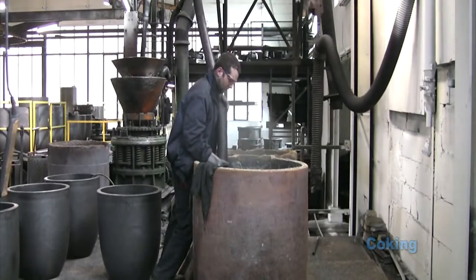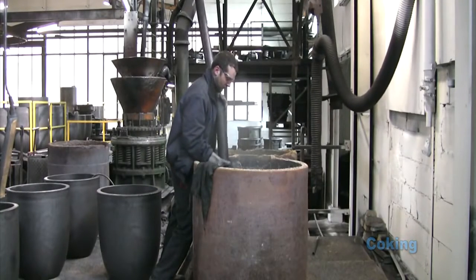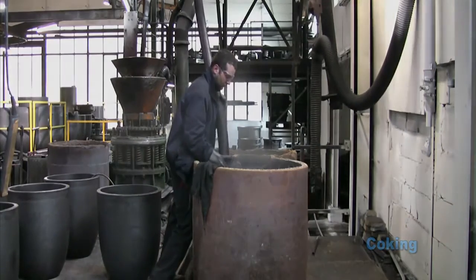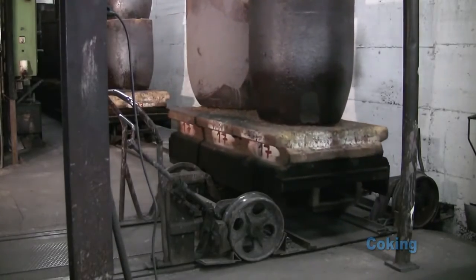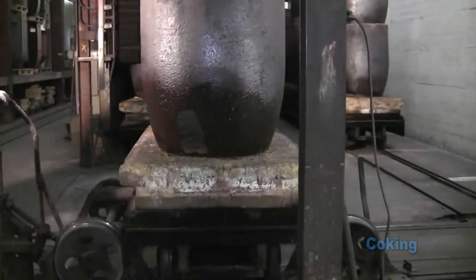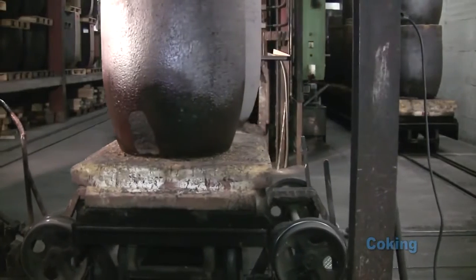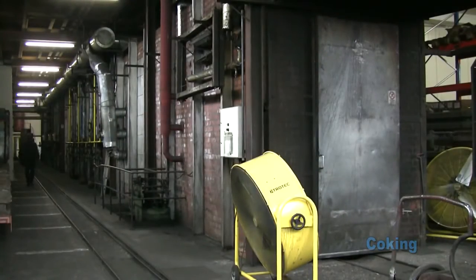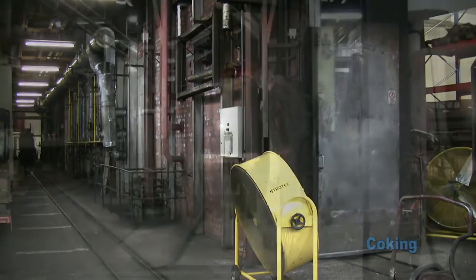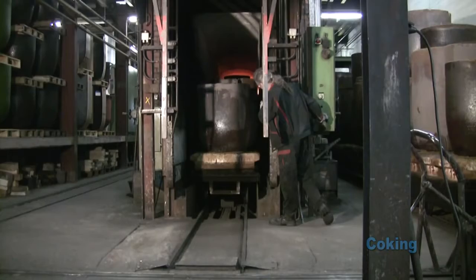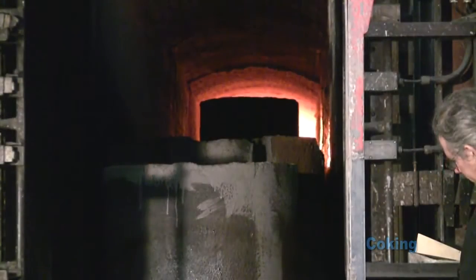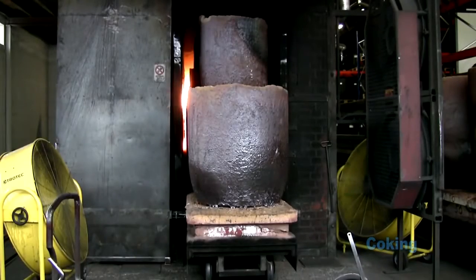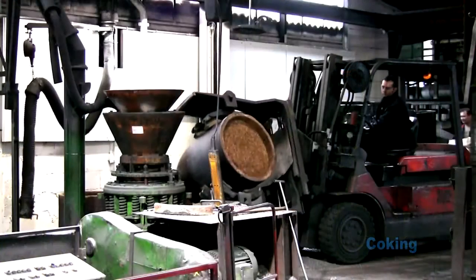A mix of bauxite grains is then used to fill all the spaces beneath, between, and on top of the green silicon carbide crucibles. An intricate system of rails and shuttle cars is used to move the crucibles to the entrance port of the gas-fired tunnel kiln. The kiln is 48 meters or more than 157 feet long. It operates 24/7. The green crucibles, with their bauxite covering, spend the next 2 to 3.5 days moving through the kiln, reaching sustained temperatures often exceeding 1,000 degrees Celsius or 1,800 degrees Fahrenheit.